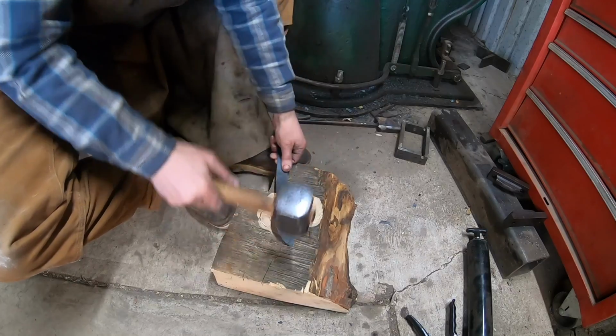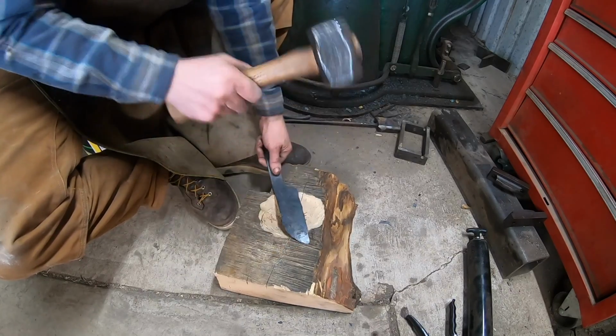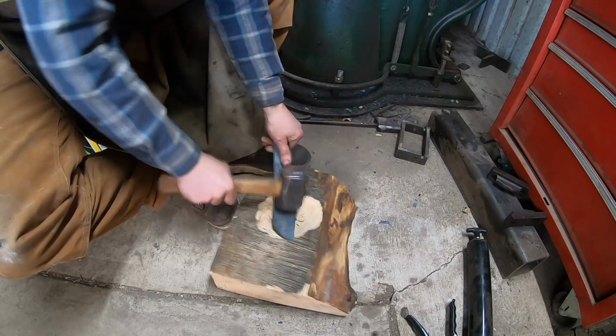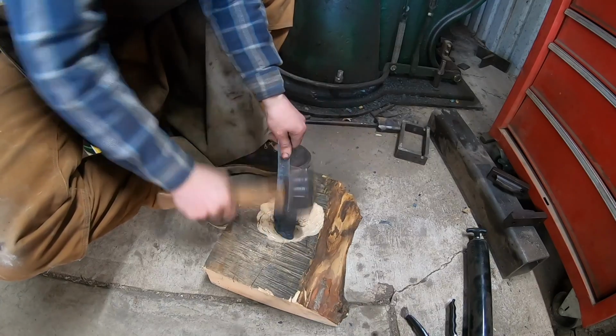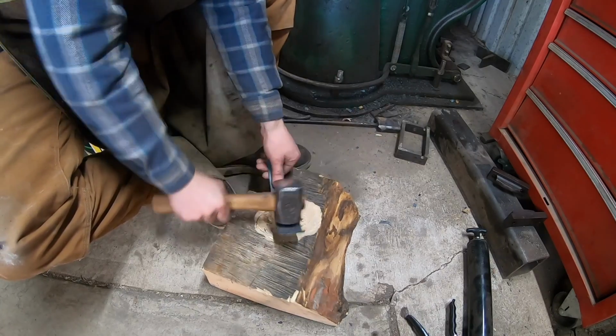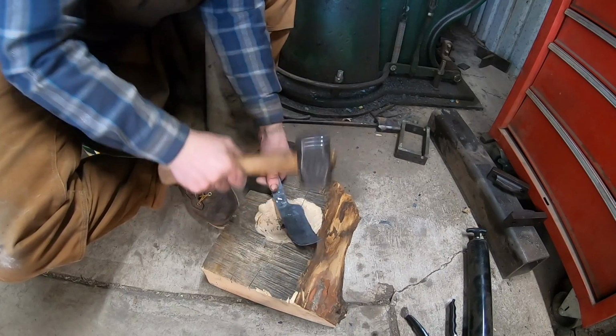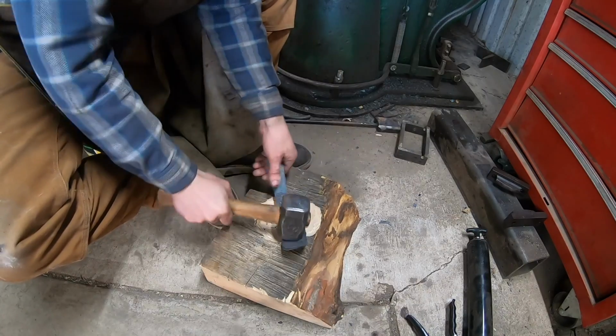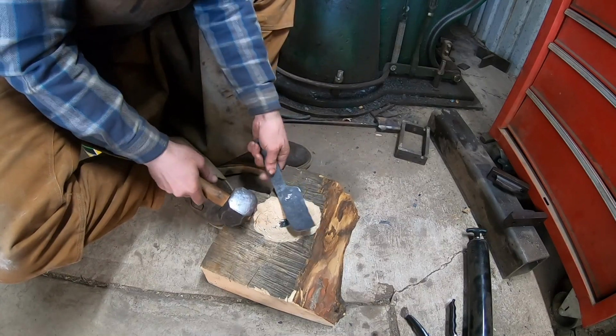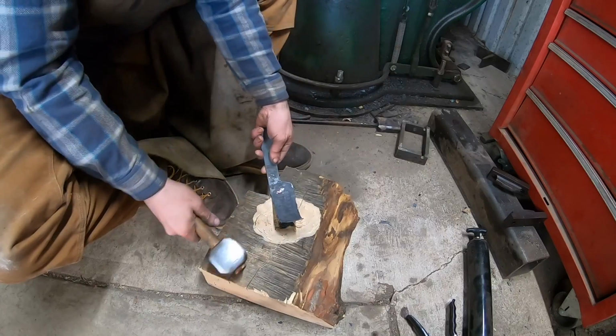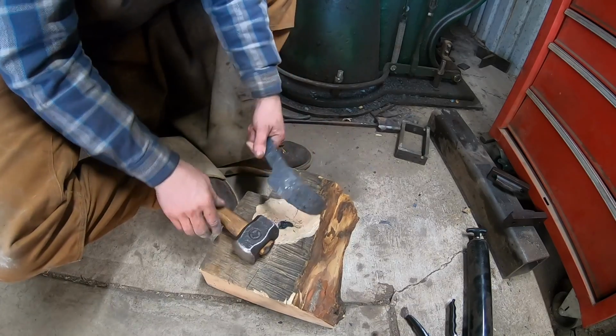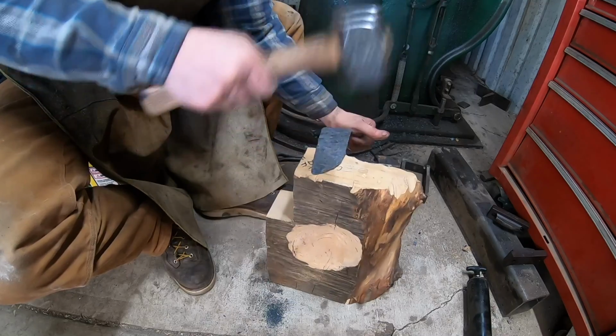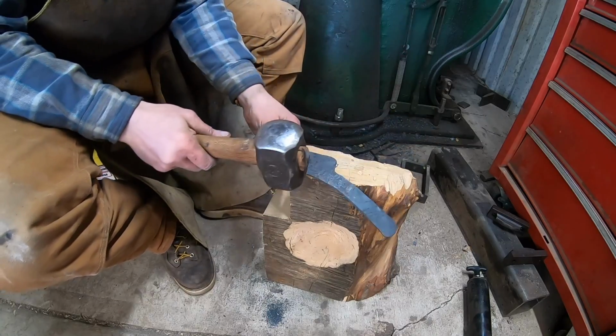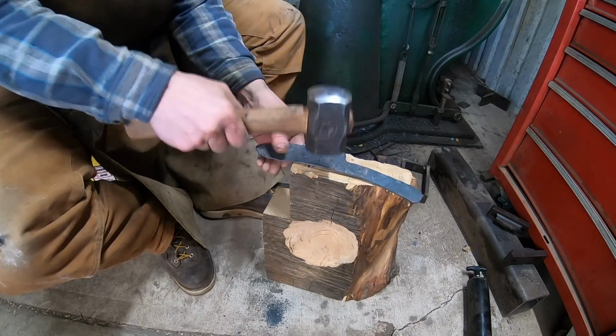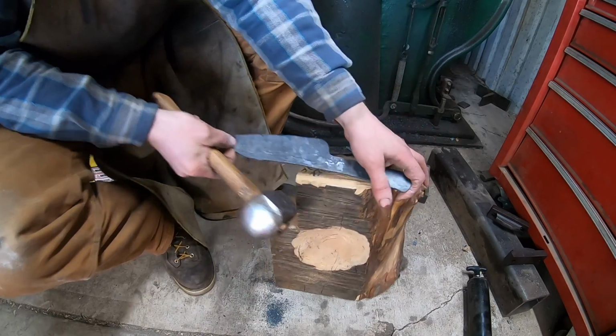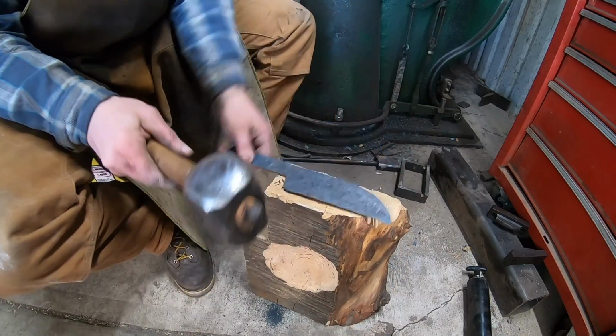Now, 2/3 of this is mild steel, but if the high carbon steel in the middle of this blade was hard at all, it would not bend like this, at least not nearly as easily. You can see the forge scale collecting in the depression of the wood block there. And once I've bent it both ways, I can straighten it out. And that took care of almost all of the forge scale.